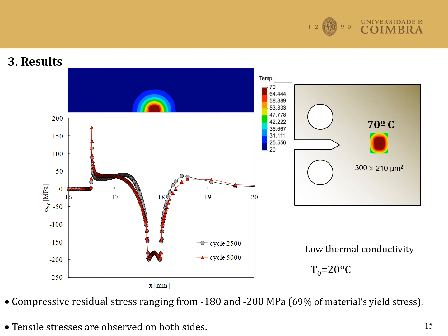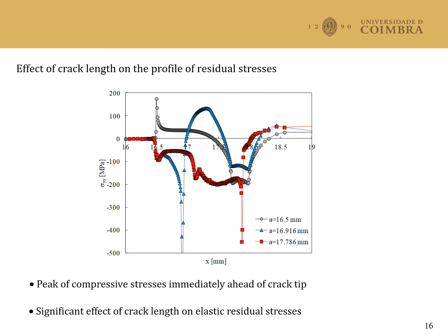This slide plots the effect of crack length on the profile of residual stresses. Three crack lengths are considered, with 16.5 mm being the initial crack length. There is always a peak of compressive residual stresses immediately ahead of the crack tip, and the initial profile of residual stresses disappears progressively with crack growth.